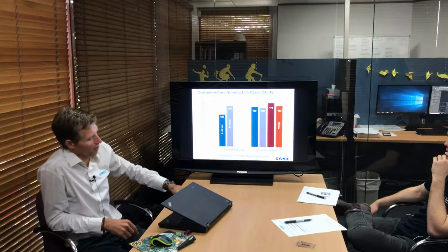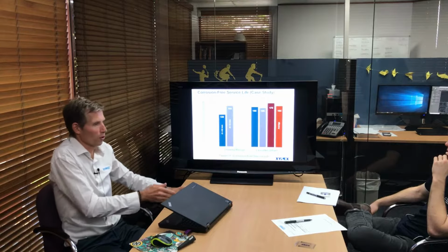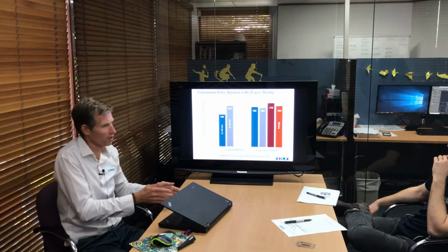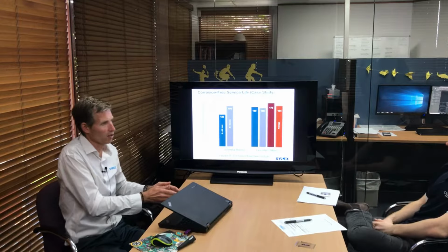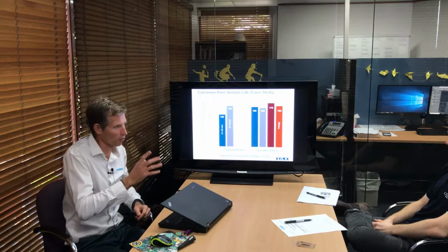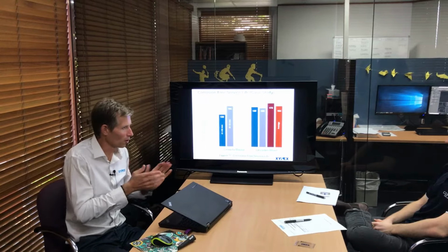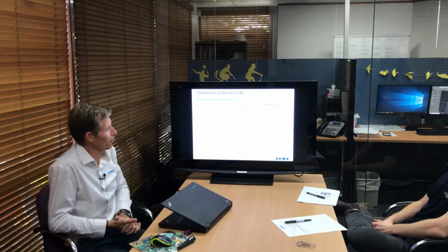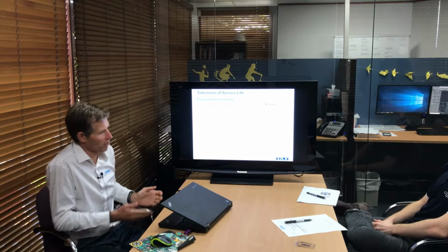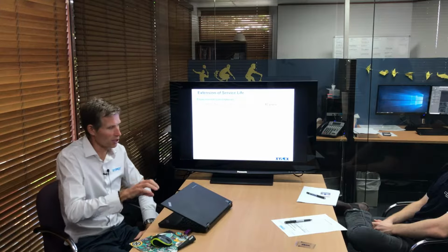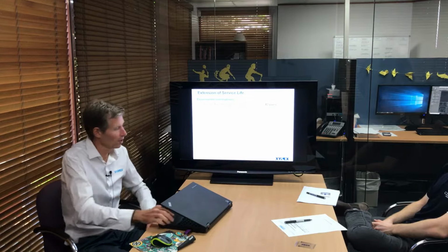So what they decided to do after that was do a little bit of cross-correlation back to a previous lab test that had been done, just to see, well, how does that relate to what we had previously told the market? So back in 2004, they engaged the University of New South Wales to do some testing on some high performance concrete. So it's 40 MPa, 30% slag concrete. On that experiment, for a normal 40 MPa, 30% slag concrete, the predicted corrosion-free service life would be something like 42 years. Now that doesn't mean the structure's going to fall to bits, it just means that's when you'll get the initial onset of corrosion take place.